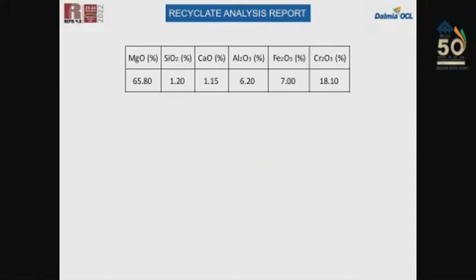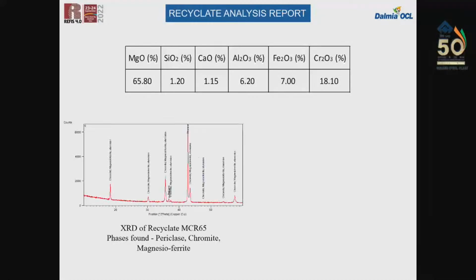So here what we have done, we have taken a recycled material. This is the chemical analysis, which is showing around 65% of magnesia and around 18% of chrome. This is the chemical analysis of the part of the refractory where there is no slag or metal. If you take a total refractory brick, the area where there is penetration has been cut away and the rest has been used.